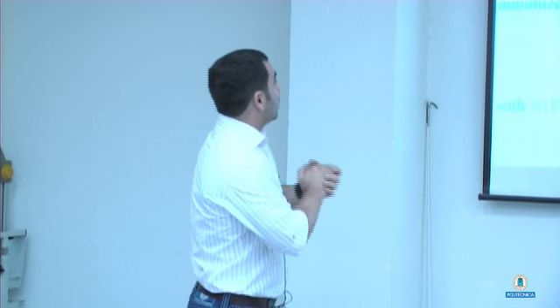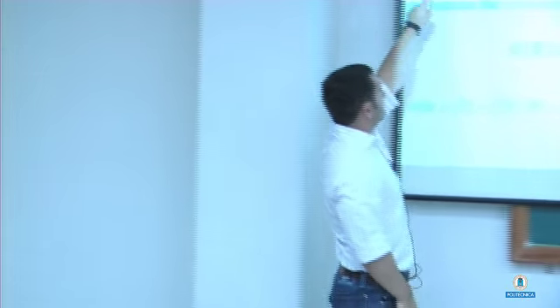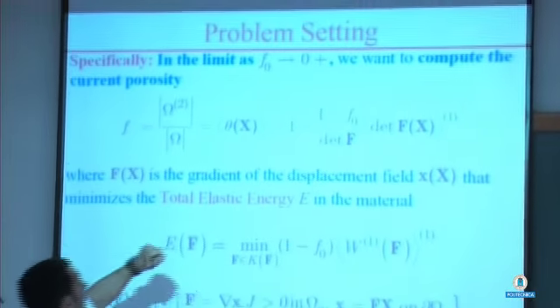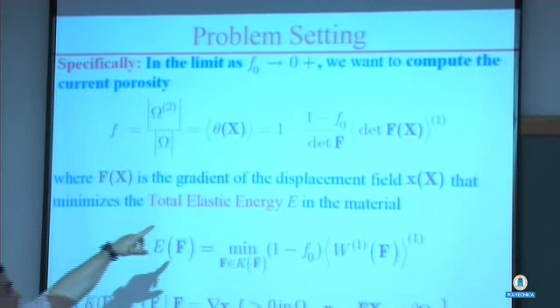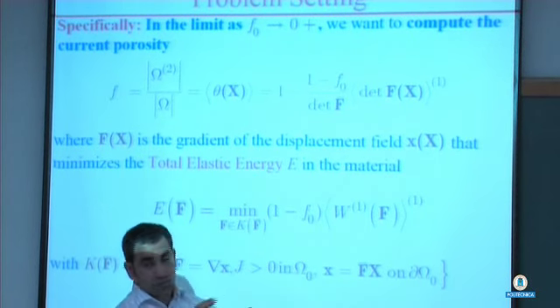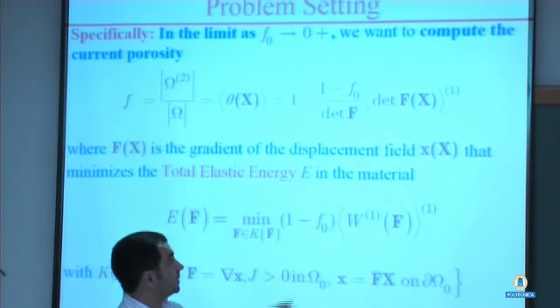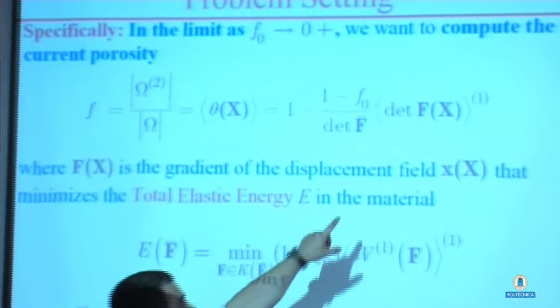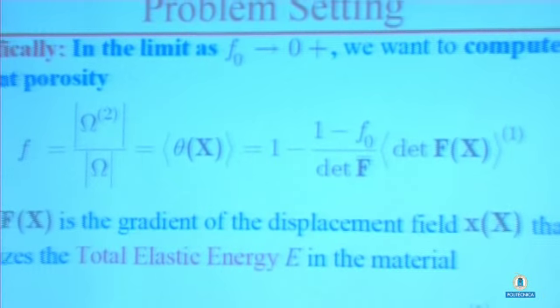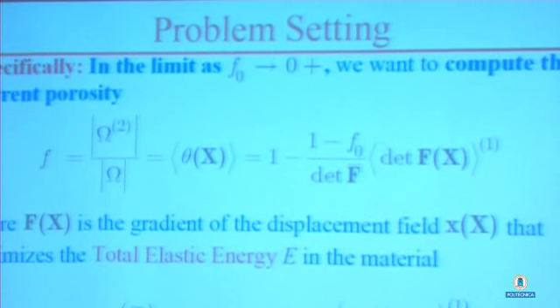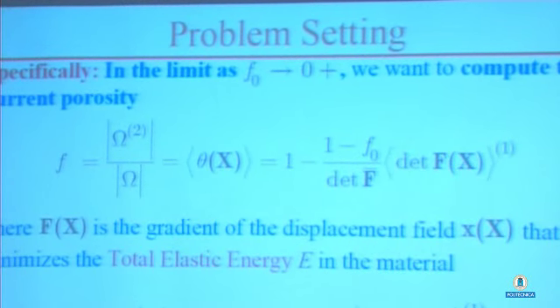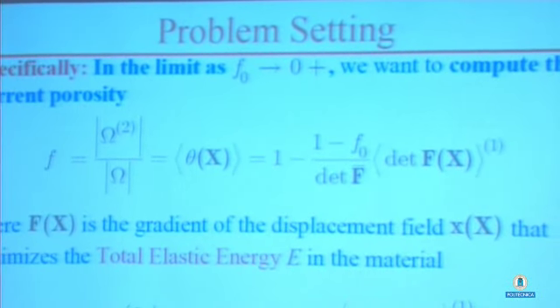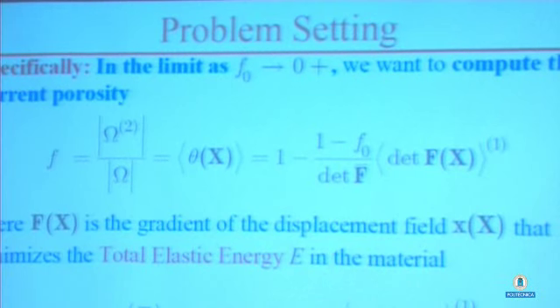More specifically, what we want to solve is for F as a function of applied loading, and it is given by this formula here. The determinant of F bar is what you apply on the boundary. F naught, again, is the initial porosity. And here we have the volume average over the matrix of the determinant of F of x. What is F of x? F of x is the deformation gradient of the displacement field, right? That minimizes the total elastic energy of the problem.